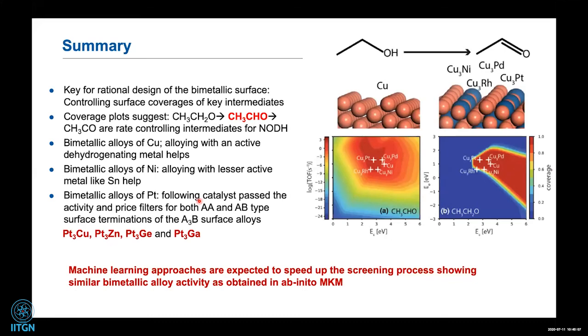Experiments have only tested platinum-zinc and platinum-copper for non-oxidative alcohol dehydrogenation, but we show two more compositions — platinum-gallium and platinum-germanium — that can be cheaper and potentially more reactive than pure platinum. This shows the power of this computational tool for high-throughput screening. The machine learning approach can dramatically accelerate this, reducing the whole screening process from high-performance computing clusters to a laptop — though building large databases will take time.